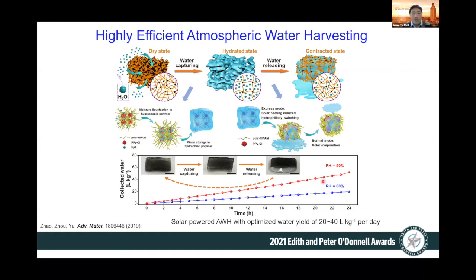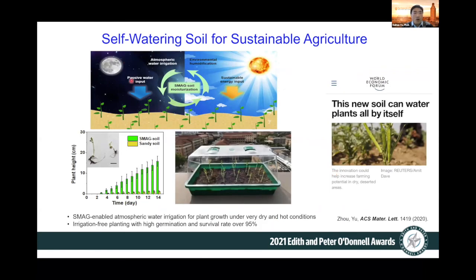So you can see, on average, we can have solar powered atmospheric water harvesting with a water yield of potentially about 20 to 40 liters per kilogram of these active gels, SMAG gels, depending on the relative humidity. And very recently, we explored this SMAG gel to make an impact on soil for sustainable agriculture.